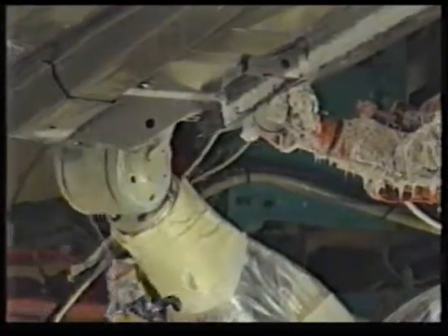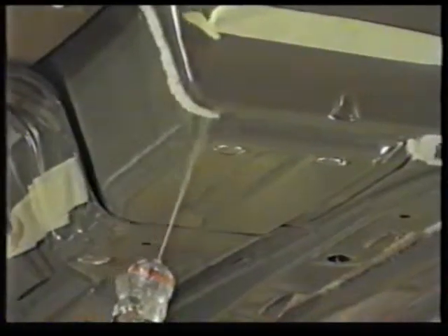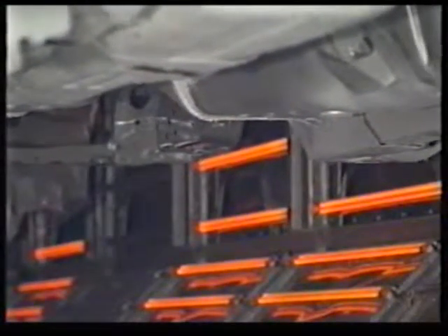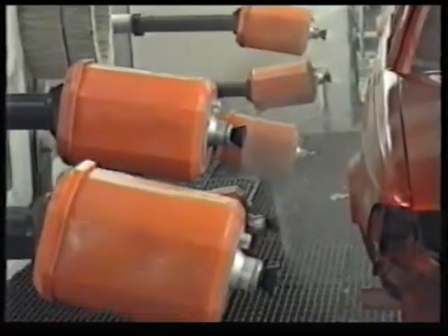anti-corrosion process. At this stage, exposed metal joints are protected with a PVC-based sealant, as is the whole of the underside of the body, to provide a tough, impact-resistant layer. A special anti-stone chip paint is also applied to vulnerable areas such as door edges and wheel arch rims, and again cured in an oven. Next, a primer surface of paint is sprayed on to create a smooth finish. Then 2 coats of colour base coat and 2 coats of clear coat follow. The total paint thickness, including the electrocoat, varies from 100 to 150 microns.